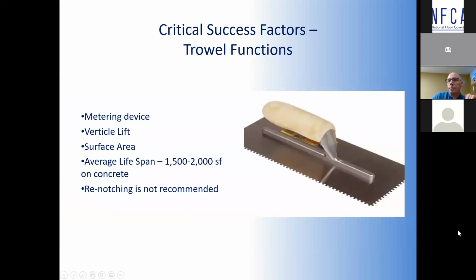So Brent, as you know, it's a V-notch trowel, and it starts with a 1/8 gap at the top, the 2 points between the V's, and you wear it out, then it becomes 1/16 between the V's. How many square feet does that take to happen? So on concrete, we actually figured it out, 1,500 to 2,000 square feet on concrete. If you're dealing with gypcrete, when I was on tools, we had gypcrete where we were changing trowels in between spreading on a vinyl floor. So they would wear out extremely quickly. So you have to be very, very careful of the lifespan of the trowel.